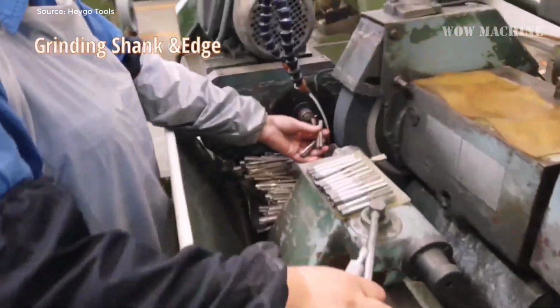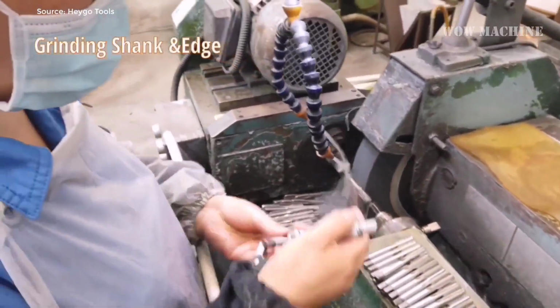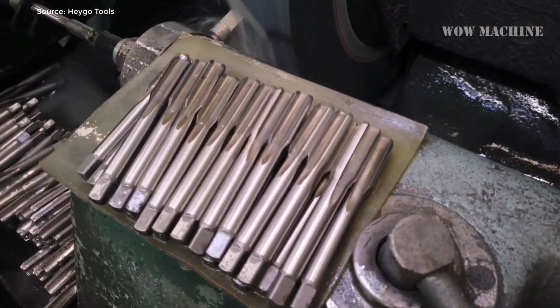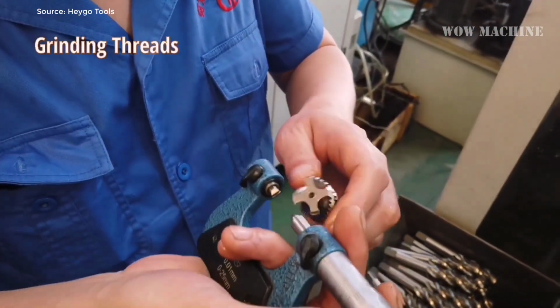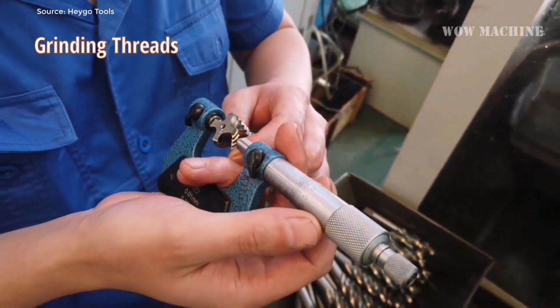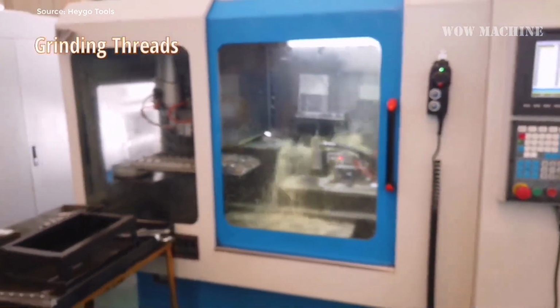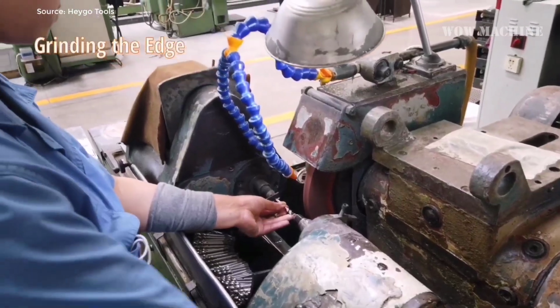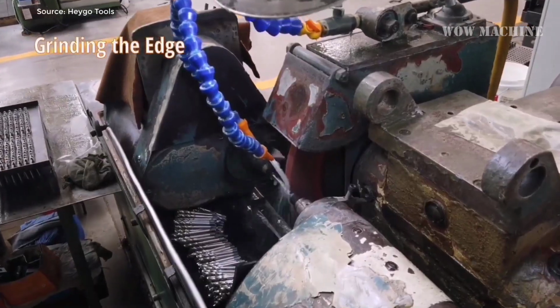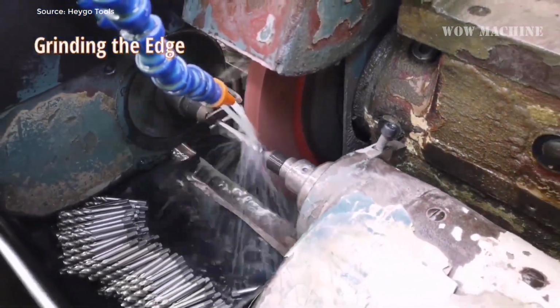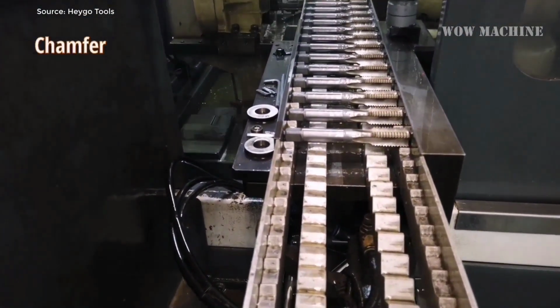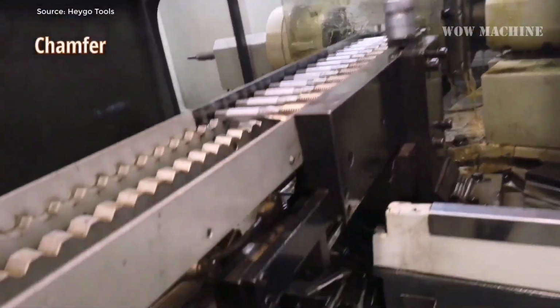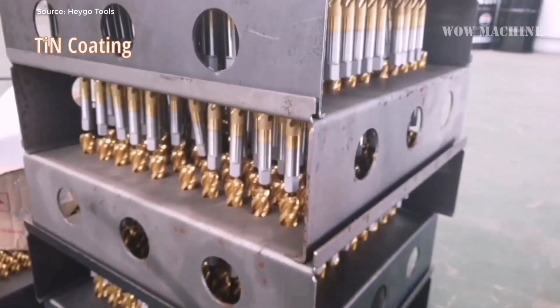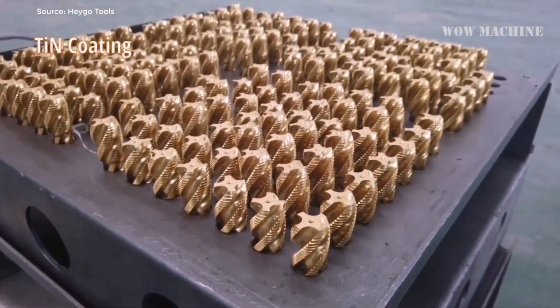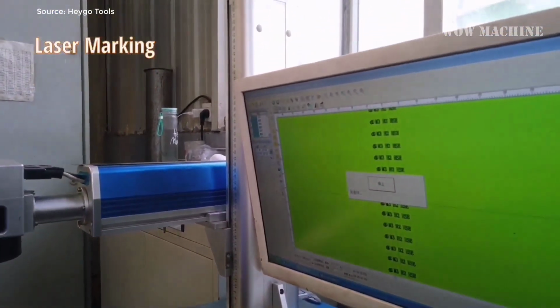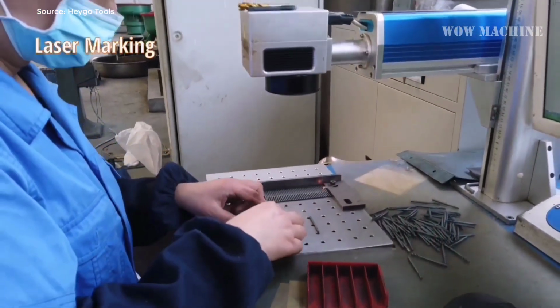Afterward, the edge is ground to refine the cutting angle and improve the tap's penetration into material. A chamfer is then applied, which helps the tap engage smoothly with the material being threaded. To further improve tool life and reduce friction, a titanium nitride TiN coating is applied. This golden-colored layer increases hardness and resists wear, especially in high-speed applications. Finally, laser marking is used to label the tap with critical specifications for easy identification. This precise, multi-step process ensures the production of high-quality thread taps capable of delivering reliable performance in various applications.